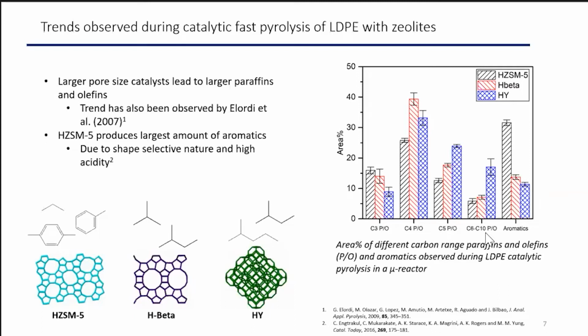And this is interesting because these C5 to C10 paraffins and olefins are potential molecules which can be used for gasoline. We also see that for the aromatics, the HZSM5 forms the highest amount of these. And this is likely due to the high acidity and the shape selective nature of this catalyst.